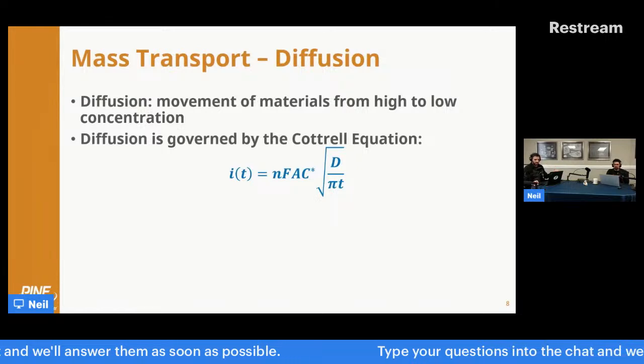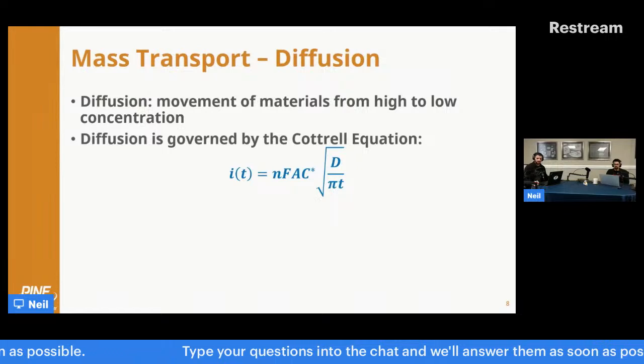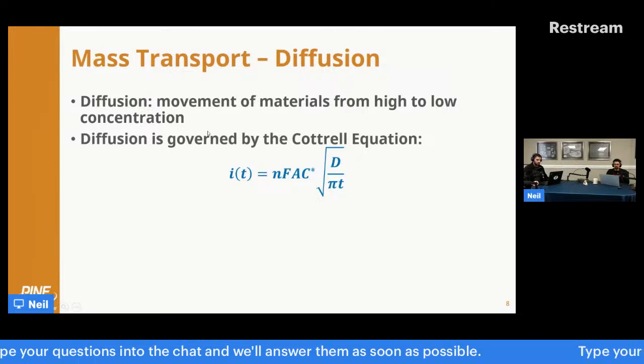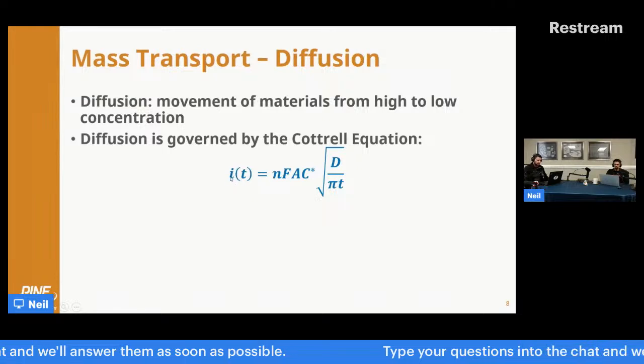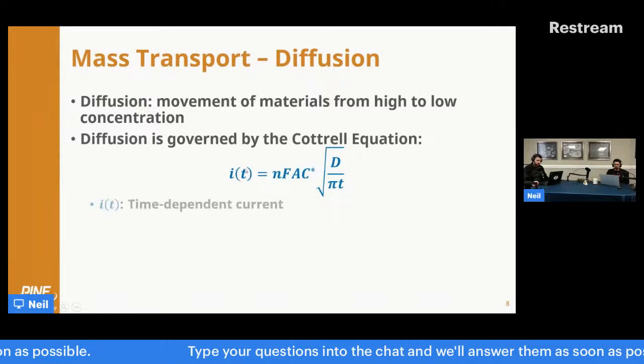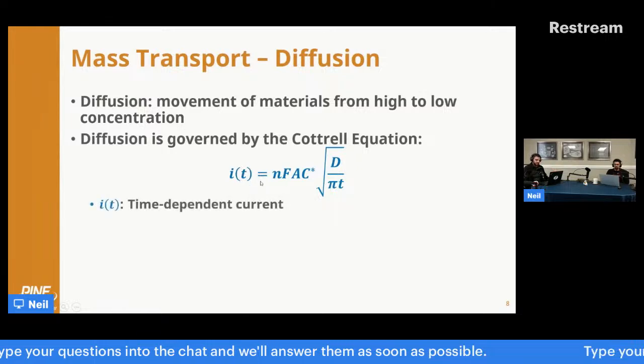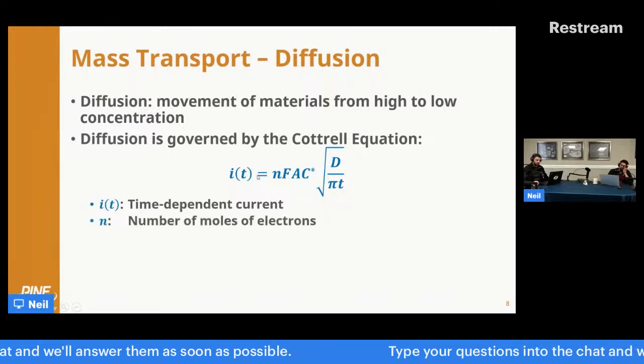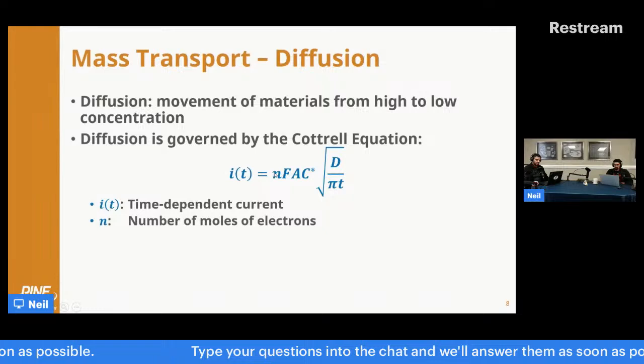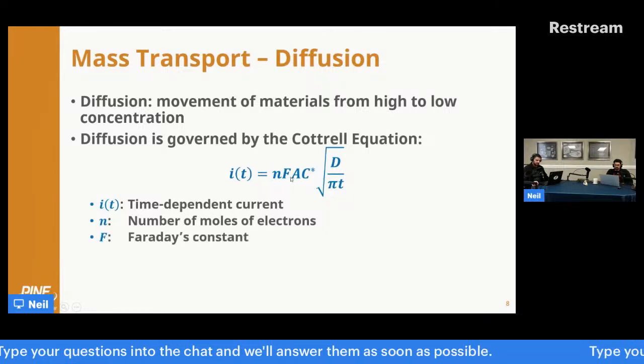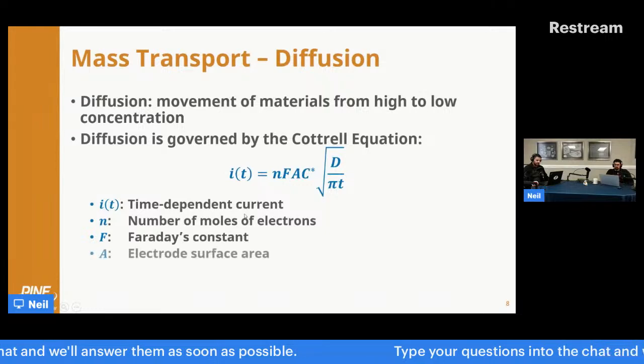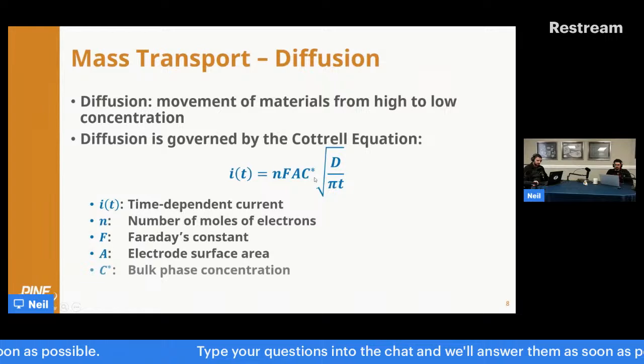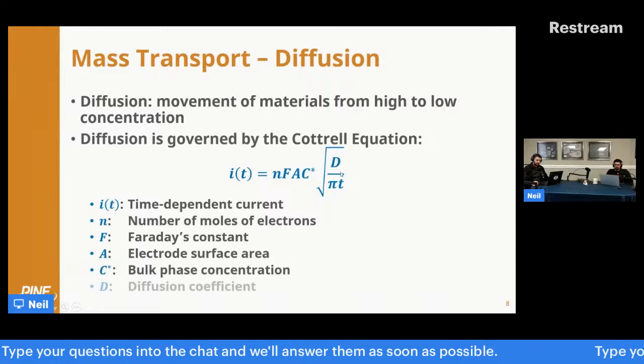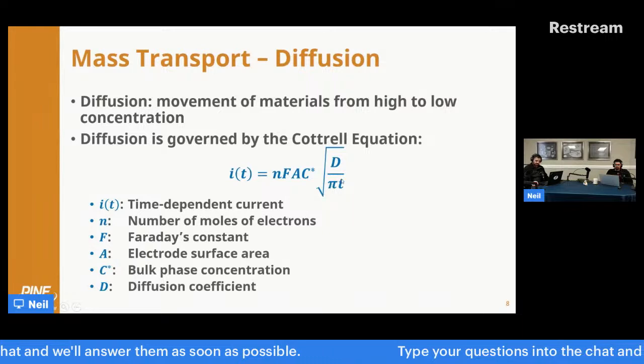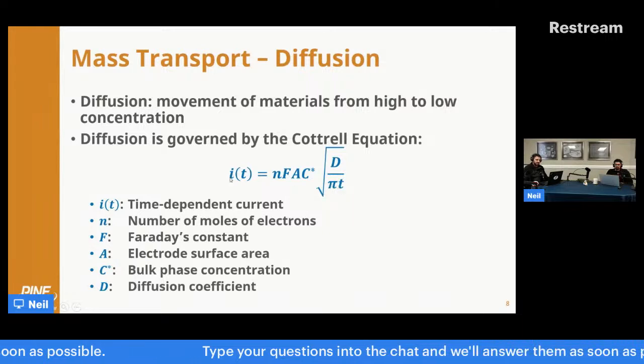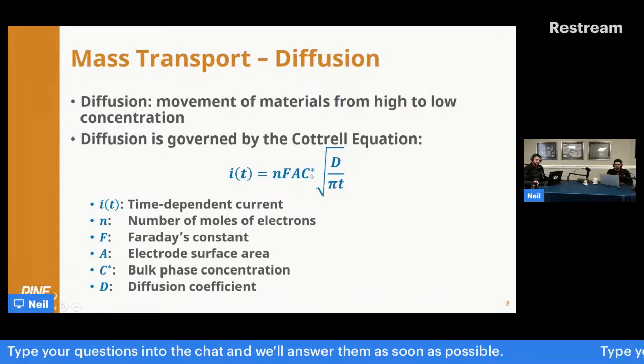and that is the ideal electrochemical equation that describes diffusion, just as the Butler-Volmer equation, as I said previously, defines kinetics. The Cottrell equation has this form, which is another function for describing the current. This time it's as a function of time instead of overpotential. The current is equivalent to the number of moles of electrons, a couple of constants, Faraday's constant, then the area of the electrode surface, the bulk phase concentration, and then the square root of the diffusion coefficient divided by pi and the time. So basically current is a function of time to the inverse square root.